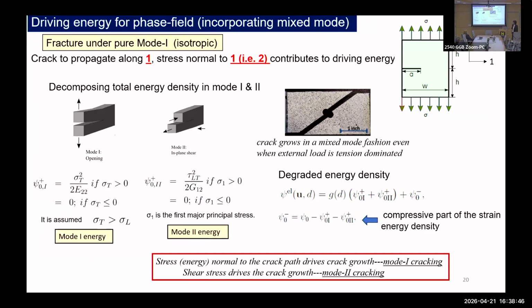In addition to that, to calculate the driving energy for the phase field crack growth, we did some modification. What we are trying to say here is that we know that the crack propagates along the fiber direction, even under pure tension-dominated mode, okay? So if the crack were to propagate under a pure mode 1 situation, then from classical fracture mechanics concepts, we know that the stress perpendicular to the crack path is responsible for driving the crack. So if the crack has to propagate longitudinally under mode 1, then the mode 1 driving energy should be dependent on the transverse stress.